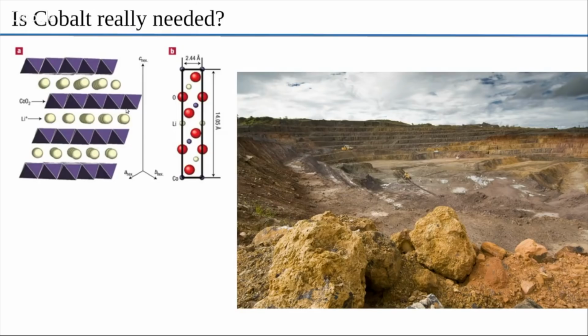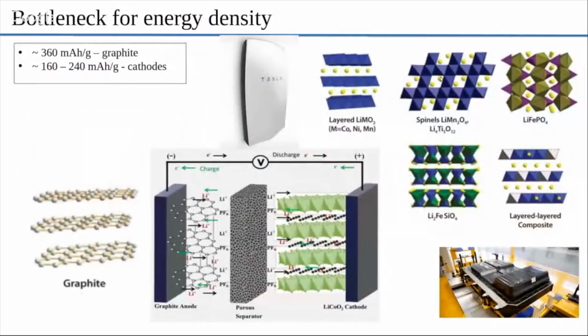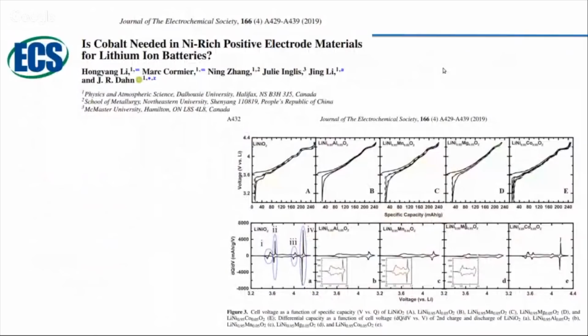And NCA is a chemistry that's still not very deeply known. Professor Dahn's group is working very extensively on this. But the community thought if you take away the cobalt from these structures, I think we showed some of these structures already. So we have layered structure cathodes, we have tunnel structures, you have spinel. They all act as a kind of scaffold where lithium ions can go and reside. So if you take away the cobalt, the consensus among the scientists was that it will compromise the structural integrity and the cycle life. But the recent study shows that you can push the nickel content really high.